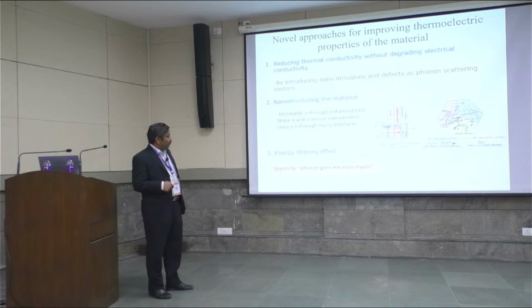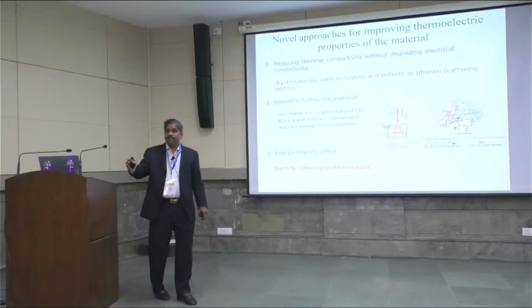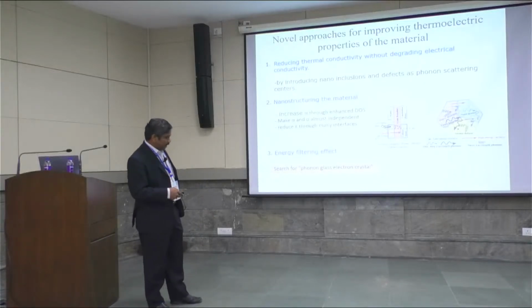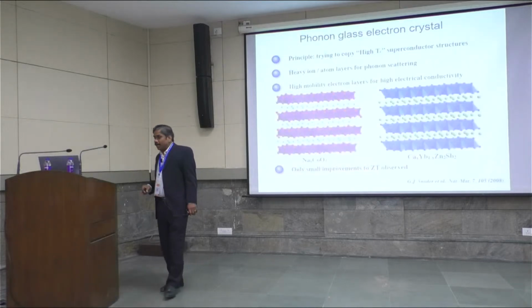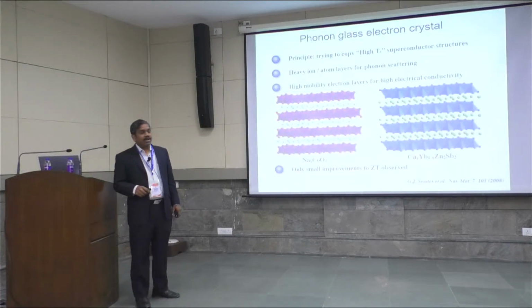And finally, the energy filtering effect, where you can have multiple kinds of interfaces, and there you can have carrier selectivity so that you can improve the Seebeck coefficient through this kind of filtering effect. So the ultimate aim of thermoelectric researchers is to find a kind of phonon glass and electron crystal, where you can have a reasonable decoupling of electron transport and phonon transport.